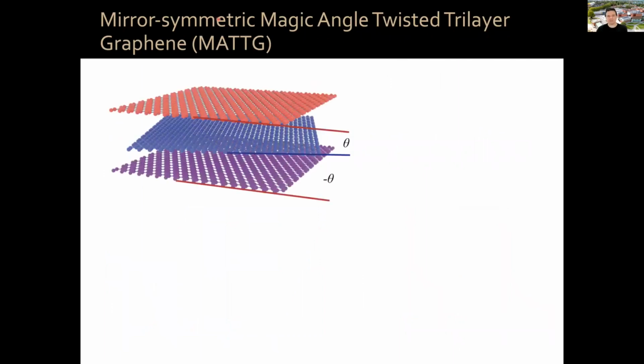Okay, so let me tell you about trilayer now. The structure that I want to talk about is mirror-symmetric magic angle twisted trilayer graphene, so MATTG. In this structure, you have the bottom and the top layers perfectly aligned on top of each other, 0 degrees between these 2. And the middle layer is twisted by an angle with respect to these 2. So from the bottom, you twist an angle minus theta and then back plus theta, so that this one is exactly on top of this one.